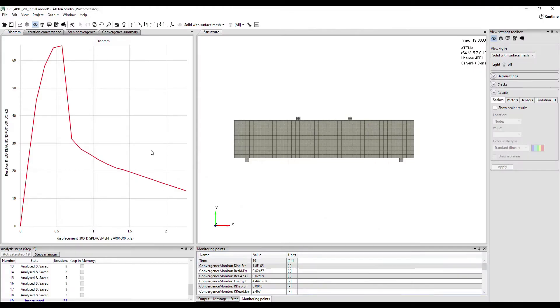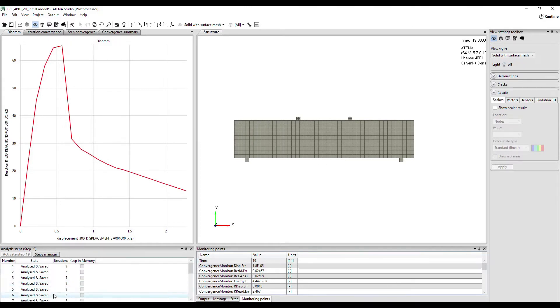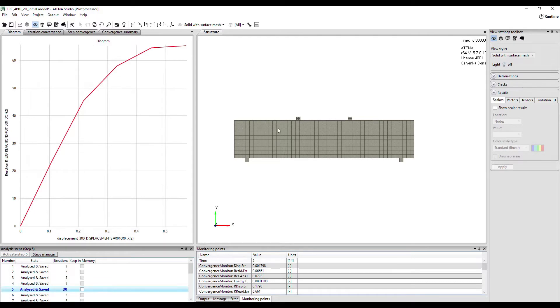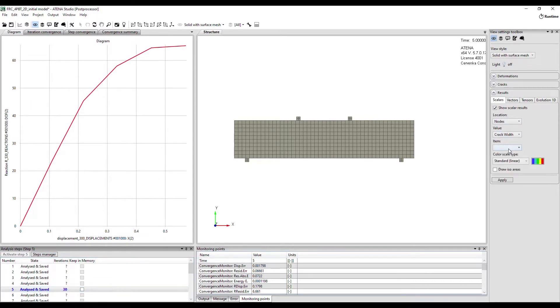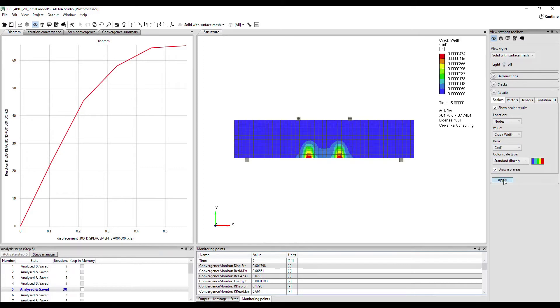It's useful to find fracture strains corresponding to points where the load should be changed. For example, we can go to the step representing the peak of the LD diagram, it's step 5, and we can show crack width to calculate fracture strain.